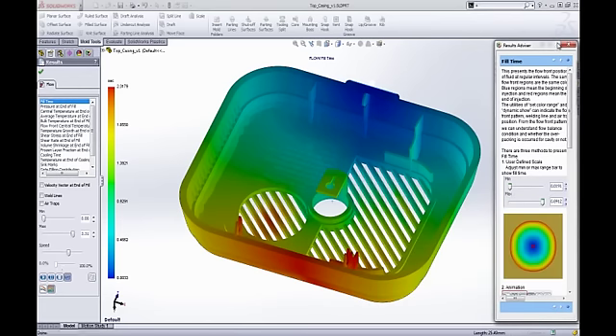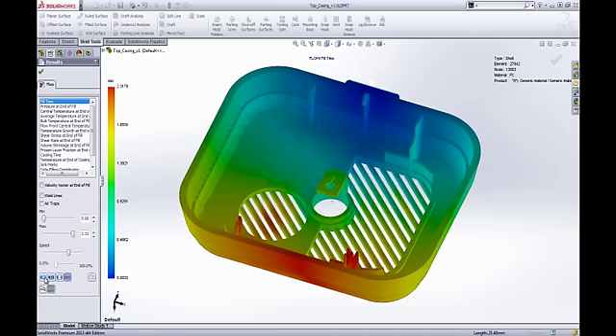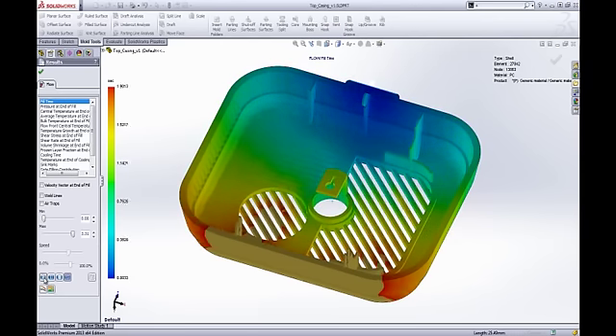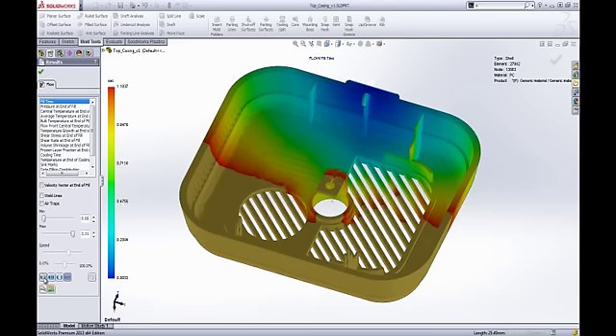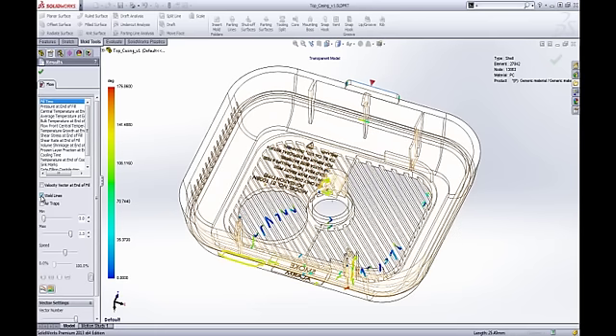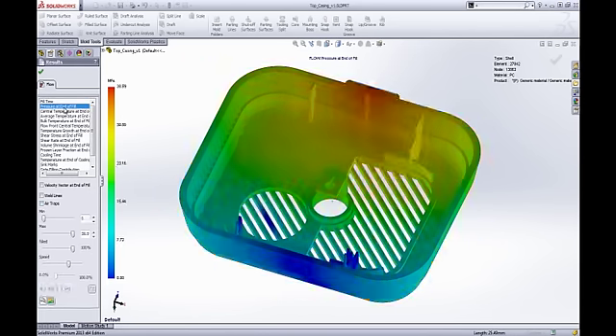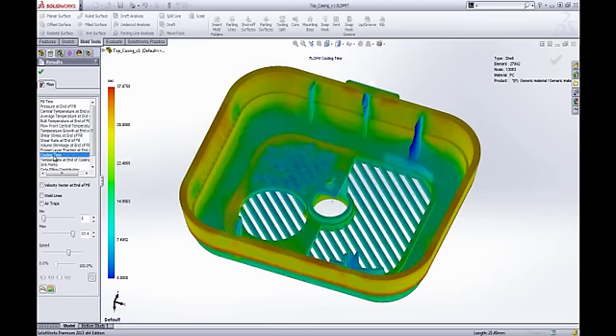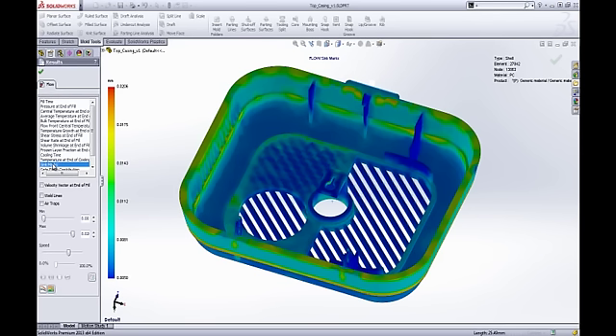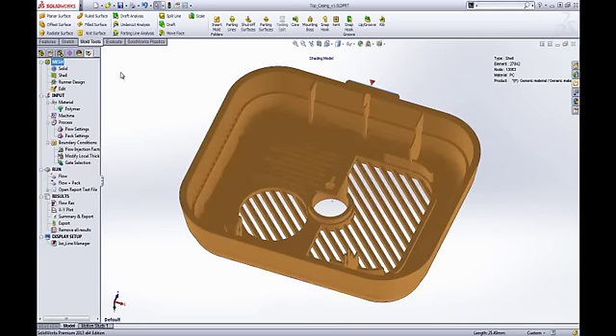The analysis is done. We have the result advisors giving us some information. Animating the fill time plot, we can see the plastic filling the cavity. We have a bit of a racetrack effect with the thickness on the side being a little thicker than the rest of the part, and a couple of weld lines on the little ribs — that could definitely be a problem. We can also look at pressure at the end of fill — it's around 40 MPa, so that's fine. We can review fill time, volume shrinkage — since the part is pretty much the same thickness everywhere, that's fine. Cooling time gives us great information about overall cycle time. Sink marks here are pretty negligible.